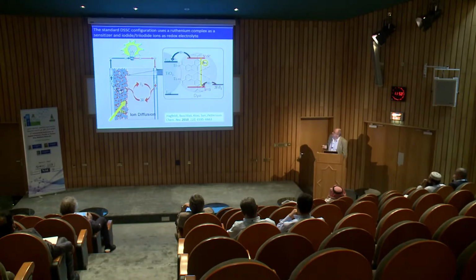A bit of the schematic, how it works. We have the contact here, the transparent conducting oxide, normally fluorine tin oxide, the TiO2 particles, about 10 micrometer thick quite often, 50-60% porosity, the size of the particles 20 to 30 nanometers. You have the dye preferably on a monolayer on the surface, and an electrolyte impregnating the pore structure.